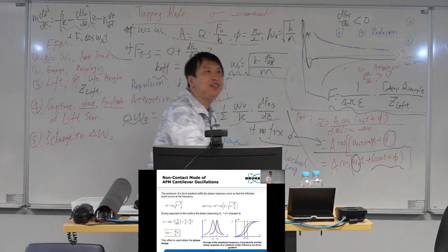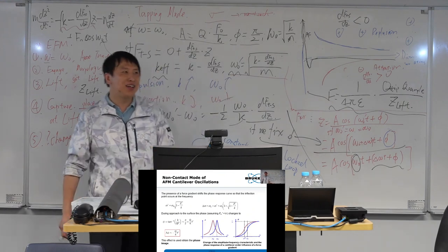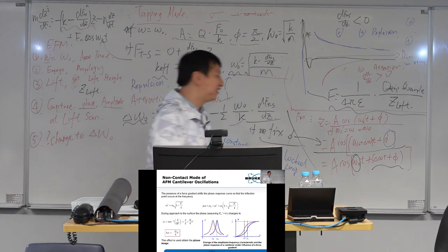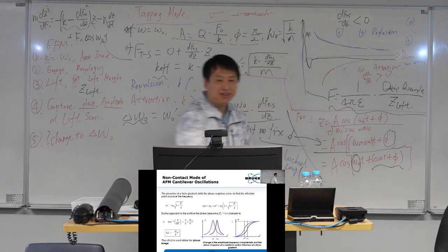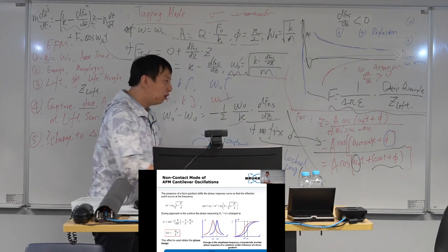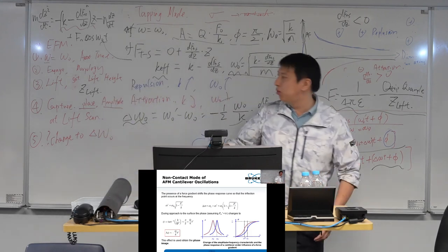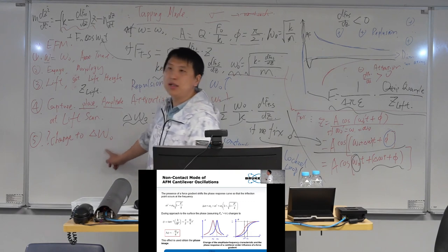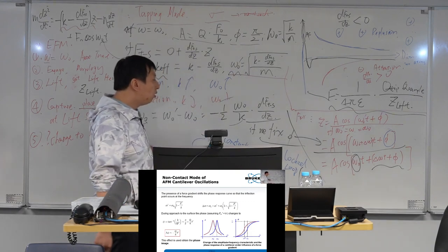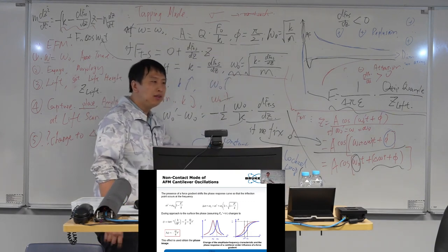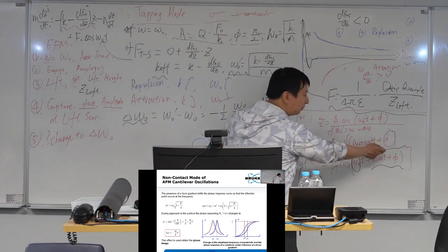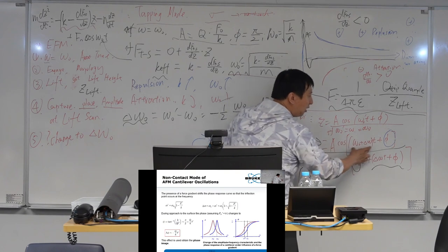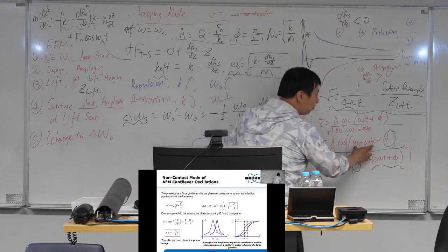You may see it in some hi-fi stuff if you play around with those. That's the famous PLL. So in the classic way, we want to detect the delta omega 0 here. We will open the phase locked loop. The phase locked loop will fix the phase term and then change the resonance. Then we change the frequency.